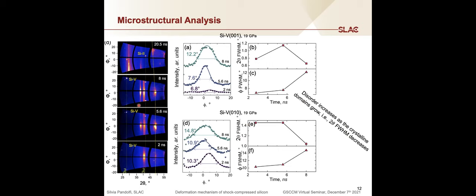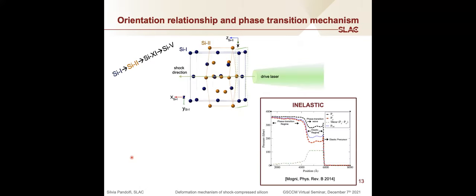And this temporal trend actually seems to suggest that, as predicted by MD simulation, the growth of the high pressure phase in silicon could happen inelastically, meaning that we first have the phase transition and then we start developing a plastic deformation at later times. So in order to see whether this peculiar microstructural evolution could be due to the inelastic deformation in silicon, we have tried to link this preferential orientation with a specific orientation relationship between the different phases, and so to a specific transition mechanism.